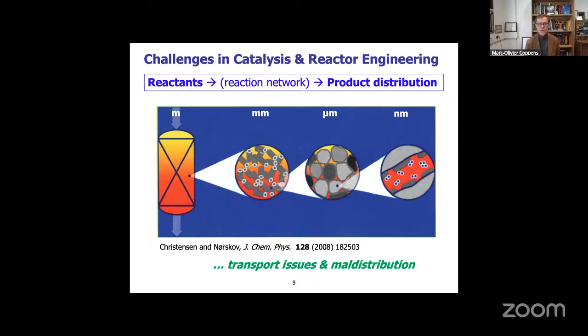And so even though we would like to go through catalysis from some reactants through a reaction network to a desired product distribution, the intrinsic kinetics may be skewed as a result of transport limitations. Transport limitations within the porous particles, so just within the nanopores that are part of particles, and these particles are part of pellets, which are in a reactor. And so you can have transport issues overall, you get maldistribution issues, and all this will skew the overall product distribution. So a description of these porous materials is extremely important.